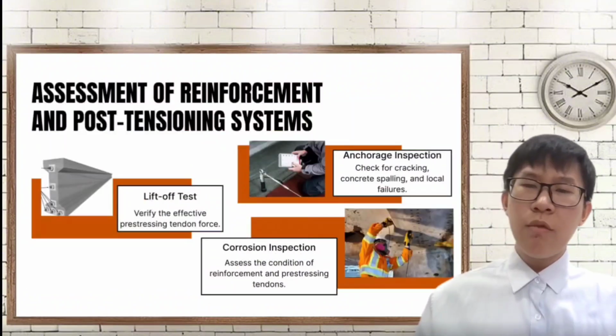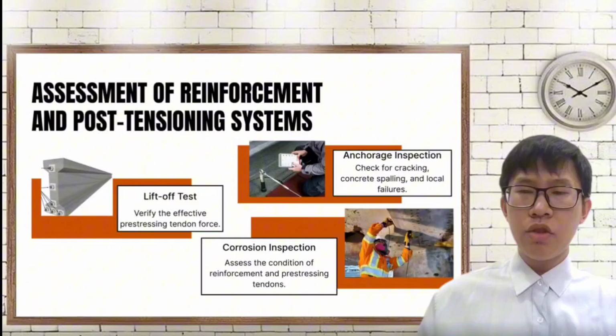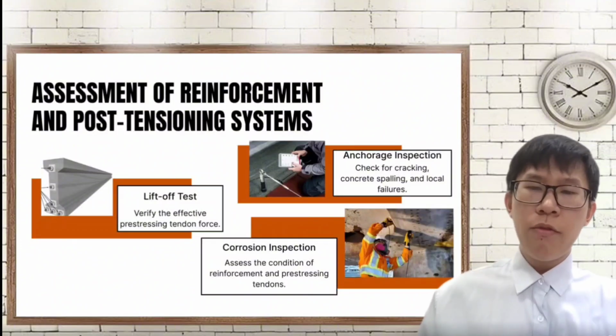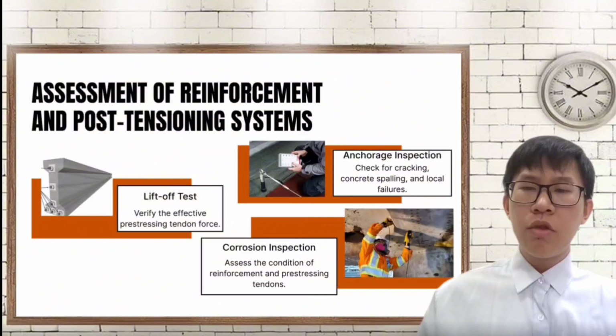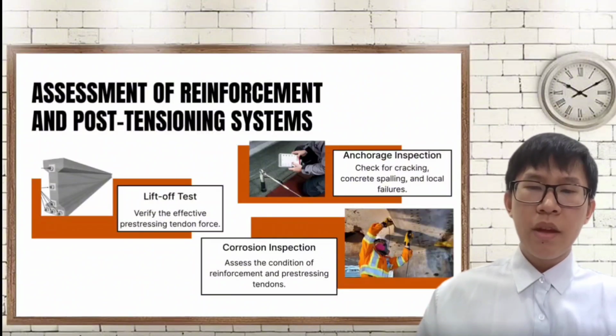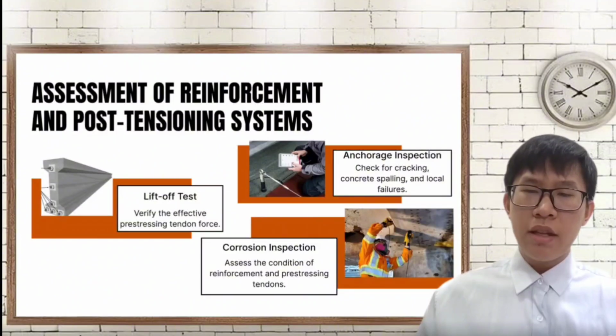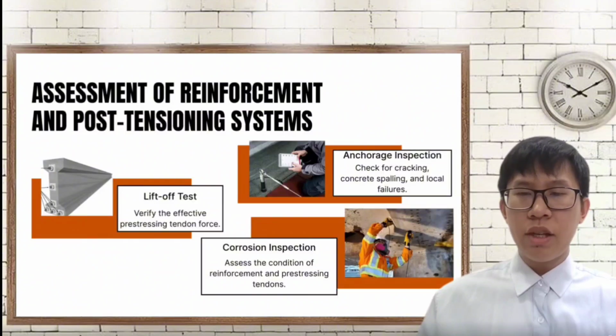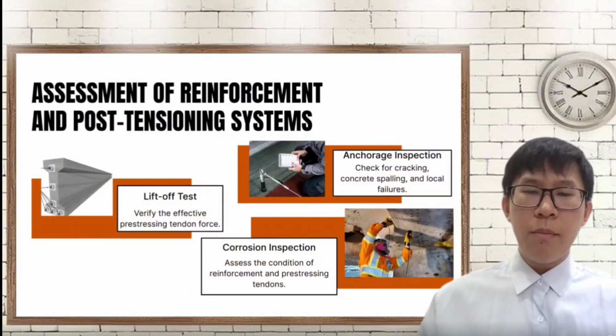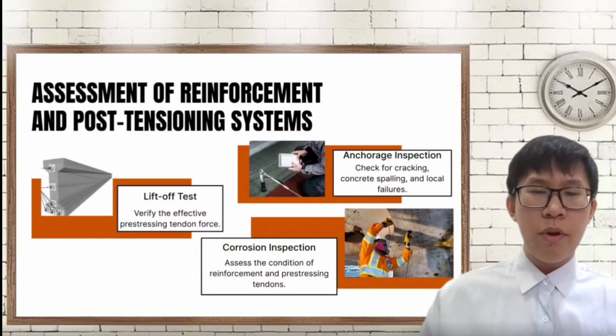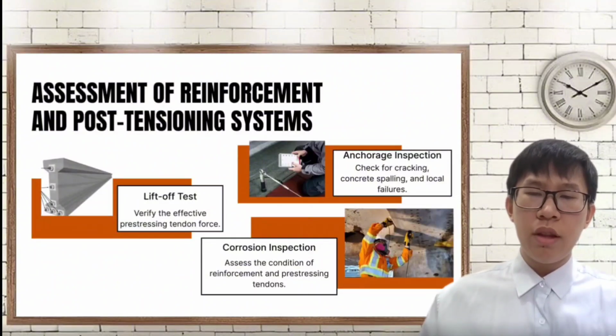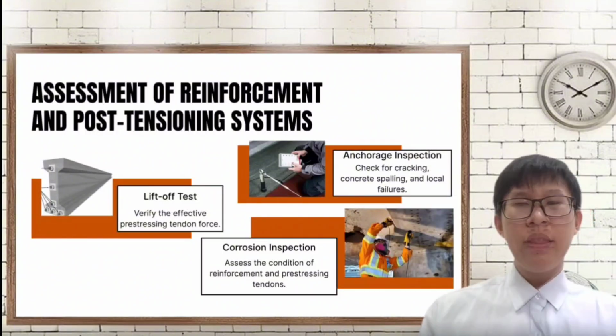Second, we closely evaluate the reinforcement and post-tensioning system. This involved an anchorage inspection to check for any critical cracking, concrete spalling, or localized failure around the anchor. We also conducted a lift-off test to precisely verify the remaining effective prestressing tendon force. Furthermore, a corrosion inspection was performed to ensure the overall integrity and condition of both the rebar and tendon.